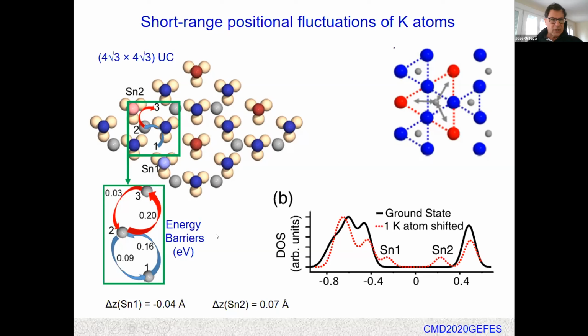For these fluctuations, we have also calculated the energy barriers for these jumps from 1 to 2 or 2 to 3. The energy barrier from 1 to 2 is 0.16 electron volts. Once the atom is in position 2, the barrier for a further jump to move away is 0.20 electron volts. But the barrier to return to the original position is only 0.09 electron volts. So if you make the calculation at 150 Kelvin, it is much more likely that once the atom is here, it will return instead of going away. So these are indeed short-range fluctuations of this type. The potassium atoms jump to a nearby position, but then they return. So the long-range order is not lost.